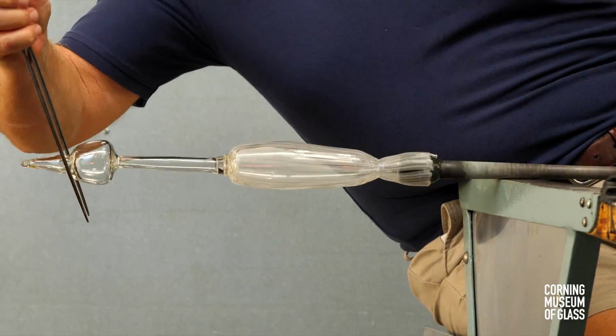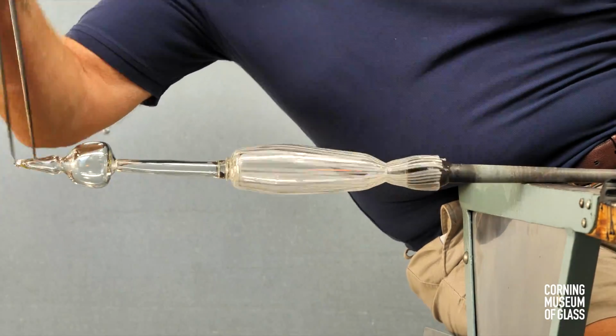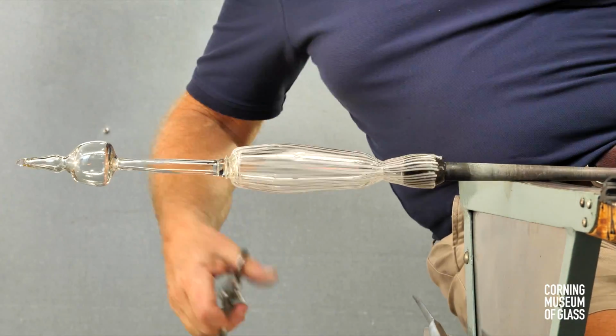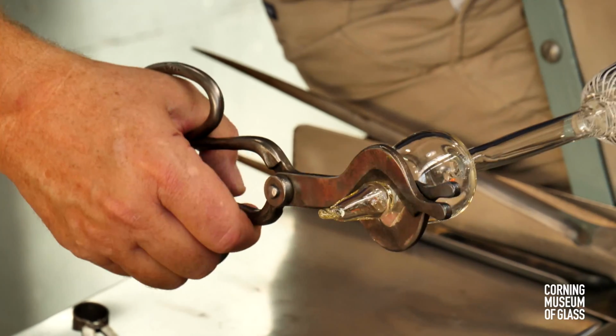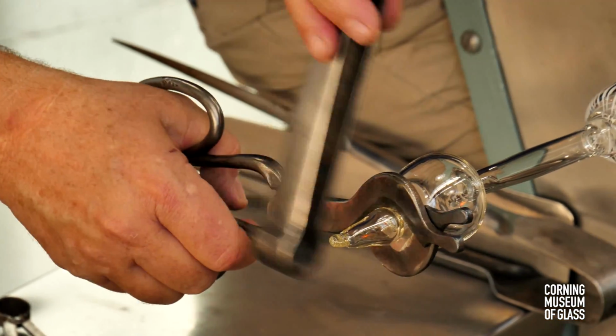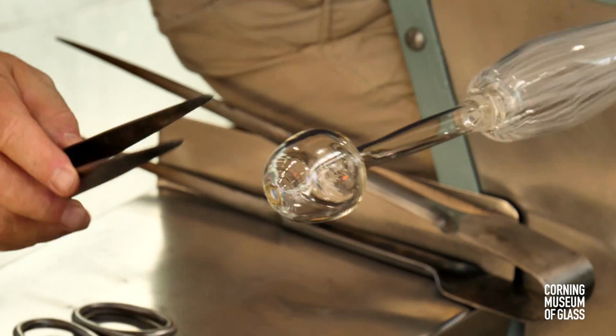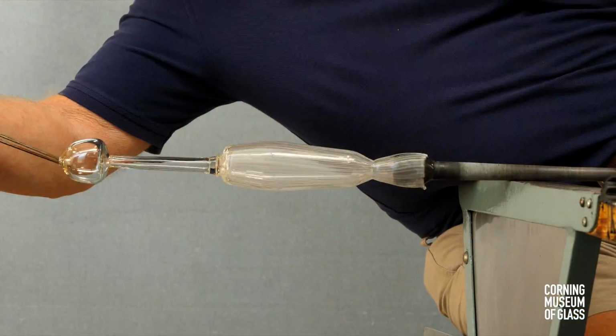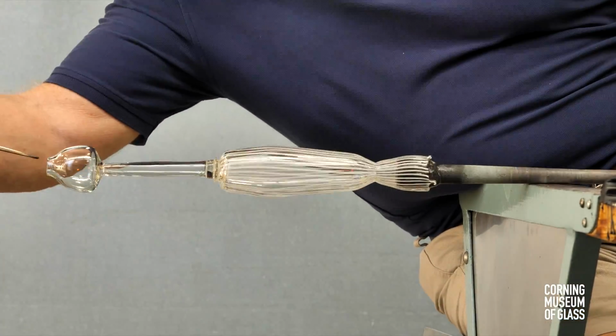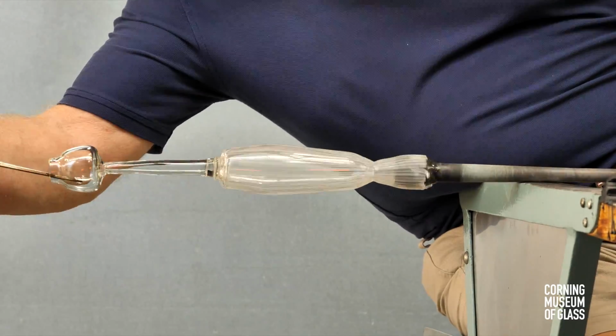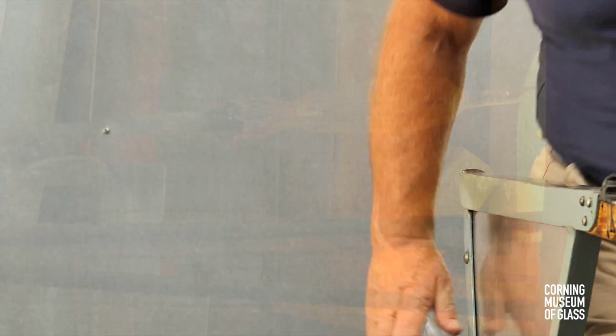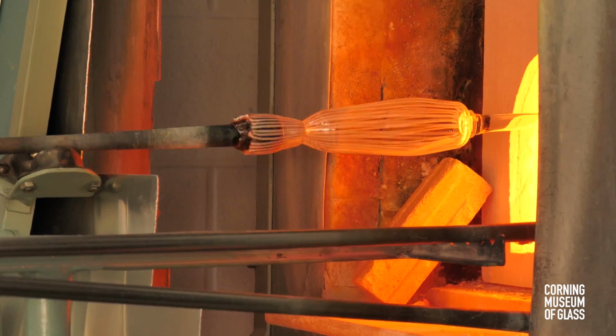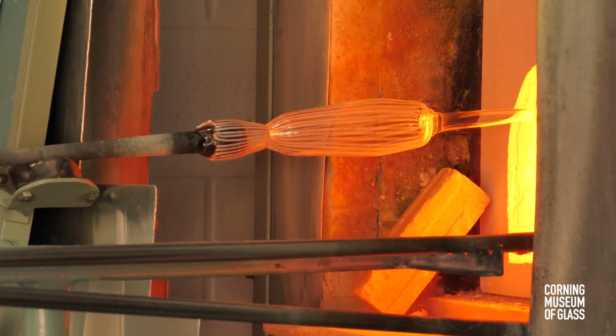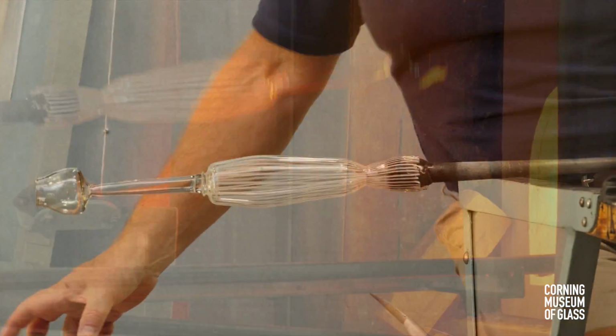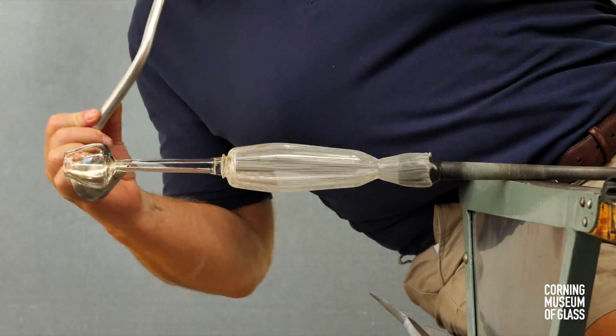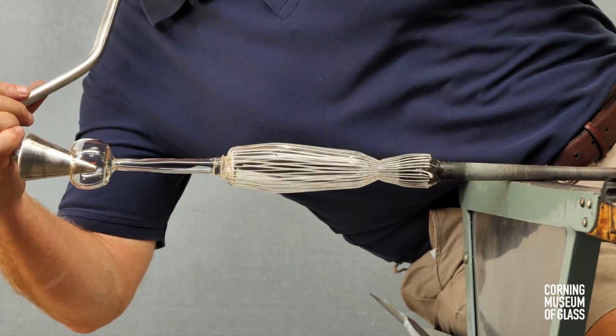A hole must be created in the end of the bubble, and this is done by making a constriction, holding the constriction with the diamond shears, and knocking off the excess glass. After reheating the bubble, the hole is opened to a diameter of about 1 inch. During this reheating, necessary to soften the foot bubble, the stem unavoidably softens. It's force-cooled with air from the soffietta.